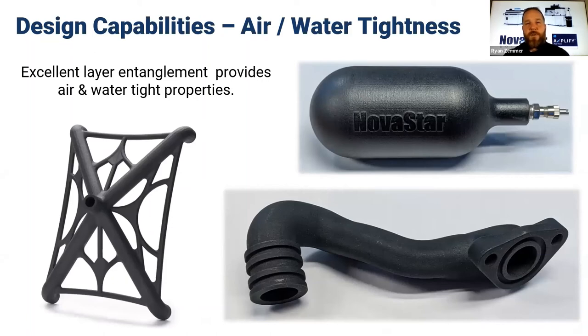And the top right corner here is a pressure chamber that we did just for our own testing and validation, similar to something like a paintball tank. That chamber only has about a 3 millimeter wall thickness, but we pressurized it up to 125 PSI, corked it for the night, and when we came back the next day, it didn't have any bleed down. So it really just speaks to how well the fusing technology itself works.